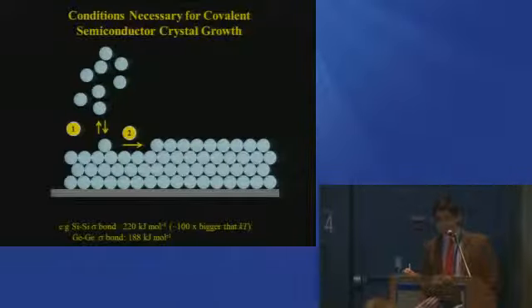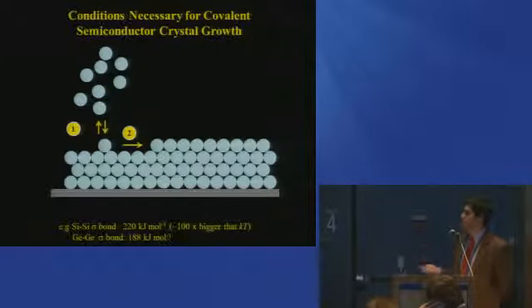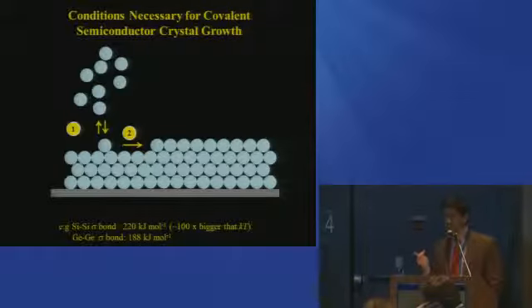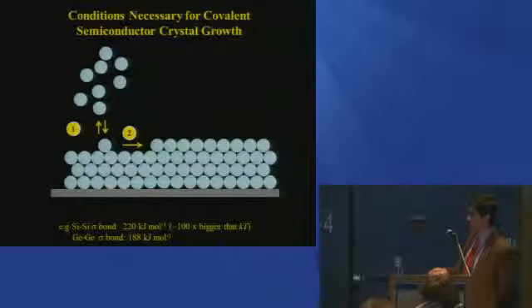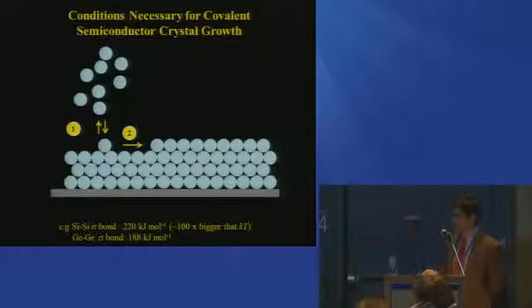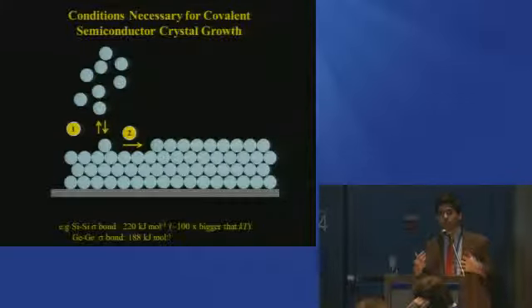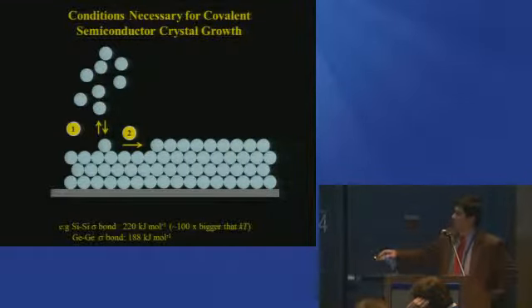The reason for that is not circumstance, and it's not just a coincidence. If you think about growing a crystal, especially a covalent crystal like silicon or germanium, you have to realize how a crystal forms. And this is where electrodeposition in the conventional sense really goes wrong. Here's a substrate, and here are the building blocks of a crystal. And when you grow a crystal on a substrate, you really have 2 pathways to make that crystal form in really high, large grains. First, there has to be some sort of active dynamic equilibrium between the solid that you're plating out and what's dissolved in solution. If you think about silicon, it's very difficult to ever imagine a solvated silicon atom in water or a common solvent. All right? So effectively, if you're trying to electrodeposit a piece of crystalline silicon, you have no chance with pathway 1. That doesn't exist.